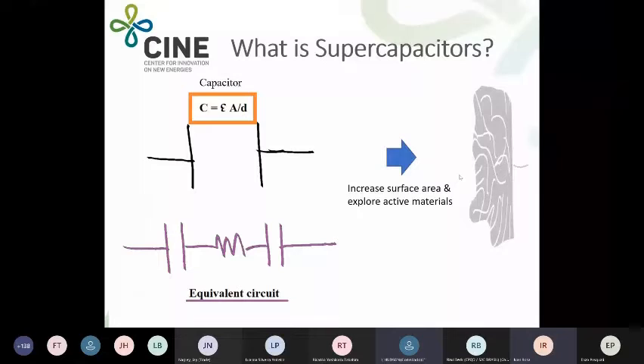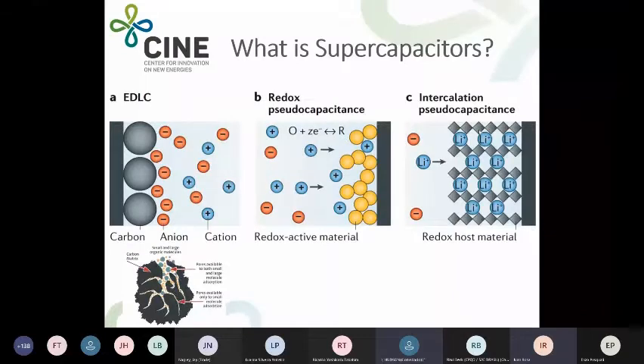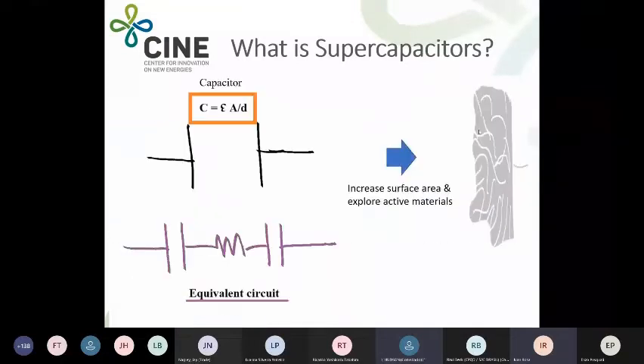What we want is a supercapacitor. For that, we change the dielectric inside the cell. Instead of plastic, we use water, which has a much higher dielectric constant, and we use an organic electrolyte, for example. We really increase the surface area with a porous, ultra high surface area material like activated carbon, which has about 2,000 square meters per gram, and this is a huge surface area compared to the conventional flat surface area. And also, we reduce this distance here.